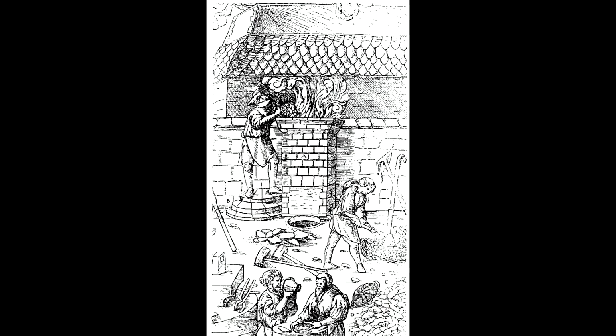Plate of an early modern bloomery, via Wikipedia, an early modern 16th century bloomery from Georgius Agricola's De Re Metallica. And so, at long last, we are getting somewhere. Our iron oxides have mostly converted by reaction with carbon monoxide and a lot of heat into pure metallic iron, while most everything that isn't pure metallic iron has grabbed some of our iron, unfortunately, or some limestone, if we have it, lowering its melting point so that it becomes liquid, dripping down to the base of the bloomery furnace, where we can tap it out.